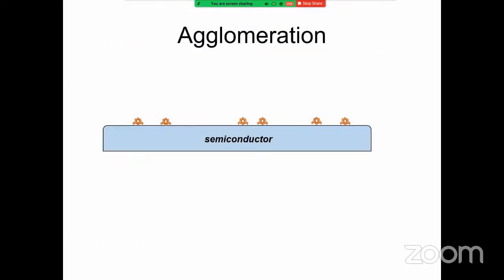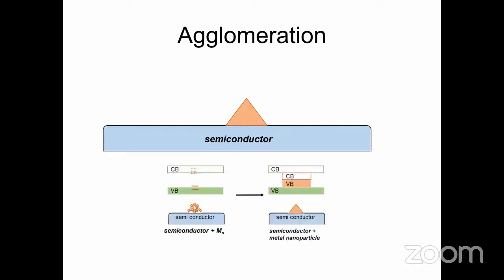We usually try to avoid aggregation as much as we can, because this is not actually our target. This is a huge challenge in nanoparticles, even at the nanoscale, because you will end up with a different electronic structure. There is no actual benefit of being precise in the gold nanocluster itself. We need to target a specific size regime to have it do a specific catalytic reaction